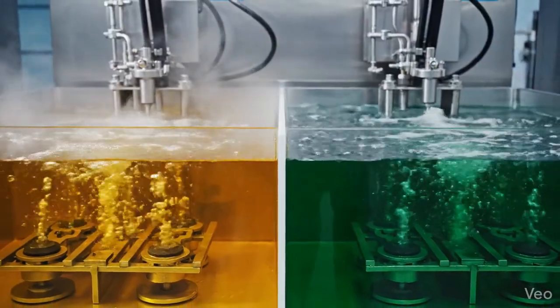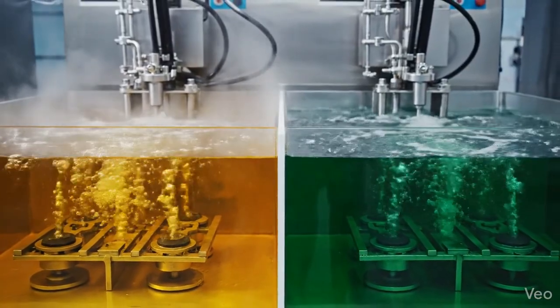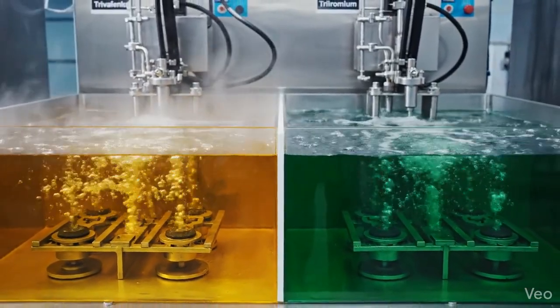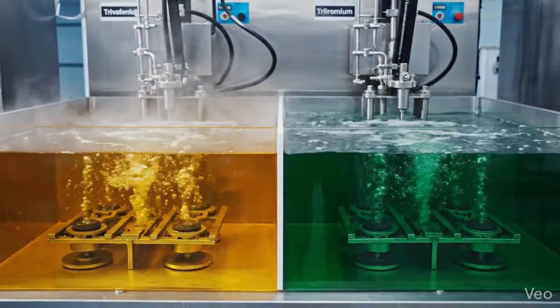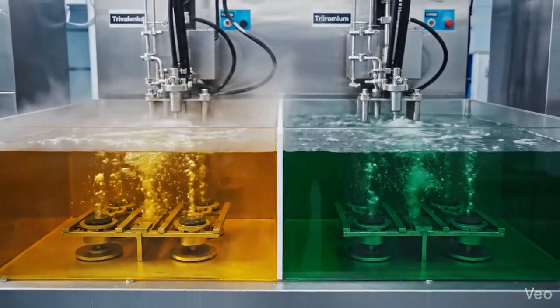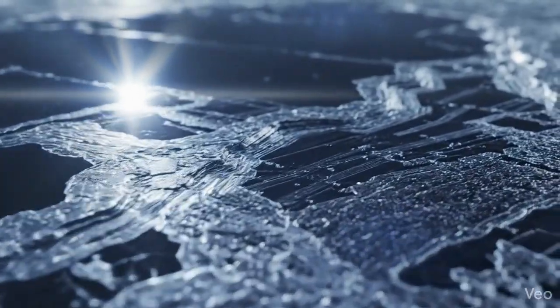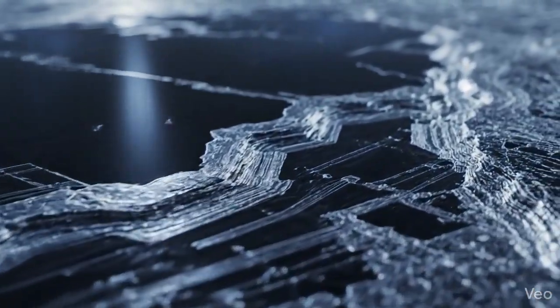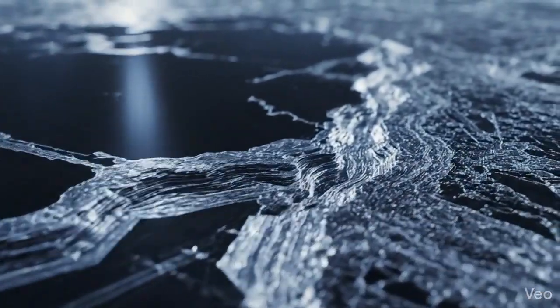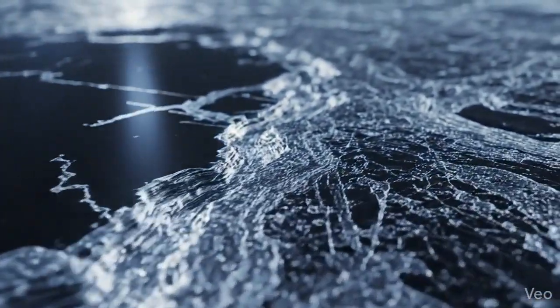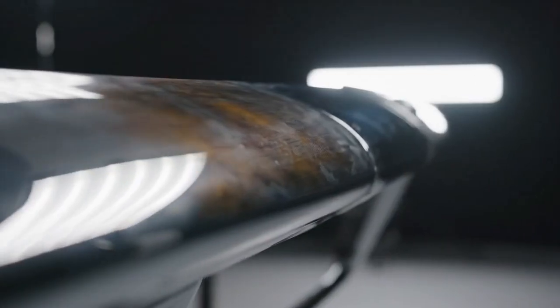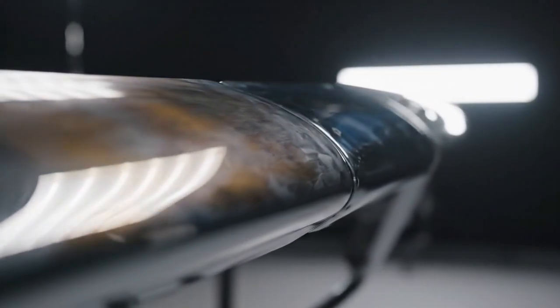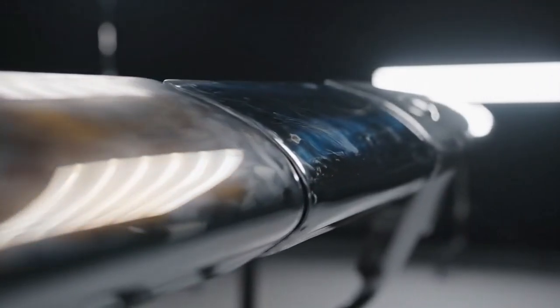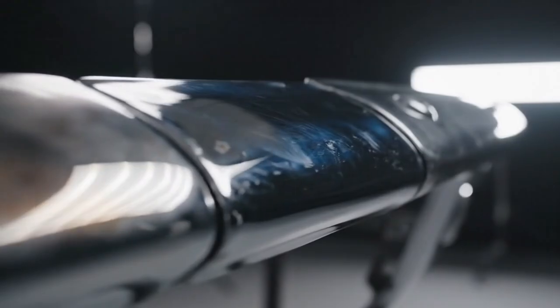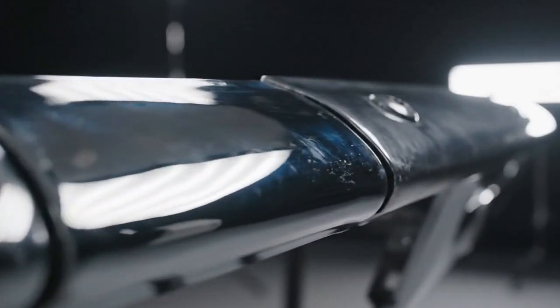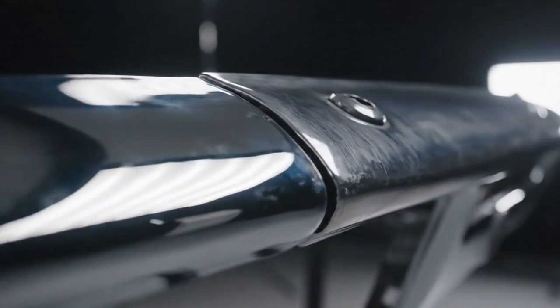The replacement process, trivalent chromium plating using Cr III, is less carcinogenic and significantly easier to manage from a regulatory standpoint. It is also measurably less durable. Trivalent chrome does not produce the same hard, tightly deposited surface layer. Its corrosion resistance in long-term salt spray testing is lower. Color matching original hex chrome with trivalent chrome is a recognized technical challenge in restoration work. The color tone sits slightly differently under light, and it shows on highly visible trim pieces when only part of a component has been replated.